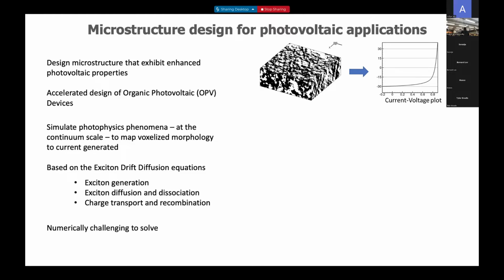Essentially, it's more electronegative, so the electron can jump ship onto the other domain. The electron passes through the white domain to the bottom. The positive charge that remains passes through the black domain to the top. That's when we say the current has been collected. And so you can clearly see that the microstructure, or the distribution of the material, typically determines how much energy you can harvest.